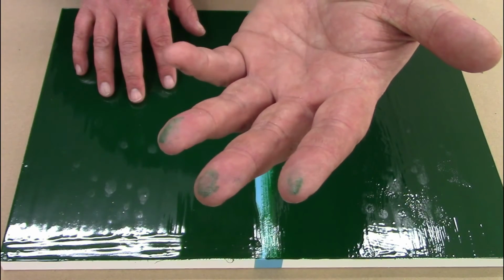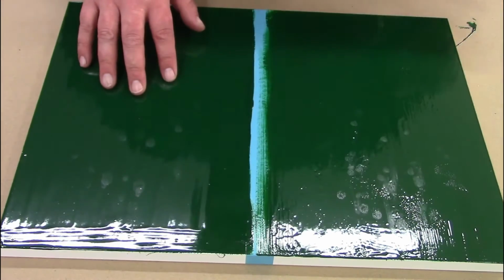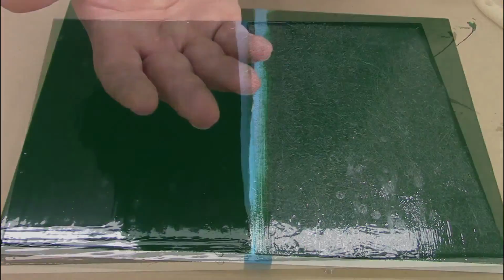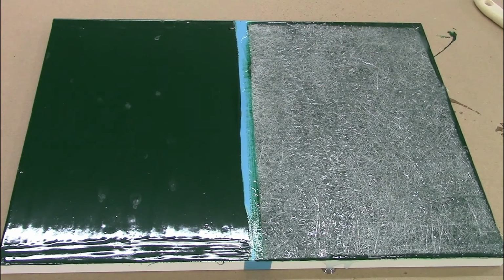3. Make sure the gel coat has fully cured before laminating. And 4. Ensure you have sufficient catalyst added to your resin. A slow curing resin will most likely attack your gel coat. And ensure all products are mixed thoroughly after adding the catalyst.